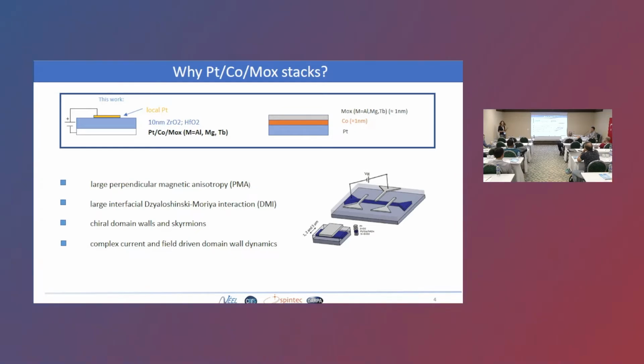First of all, because of the large magnetic anisotropy, because of the large Dzyaloshinskii-Moriya interaction that induces chiral Néel walls, as we all know, and skyrmions, of course. And we have been busy for many years in collaboration with André Thiaville in Paris to figure out the domain wall dynamics in this kind of systems that are strongly modified by the presence of DMI. But I'm not going to talk about DMI really today.